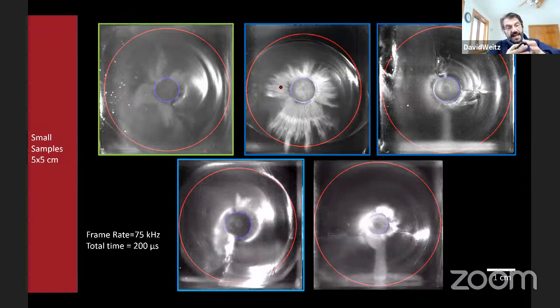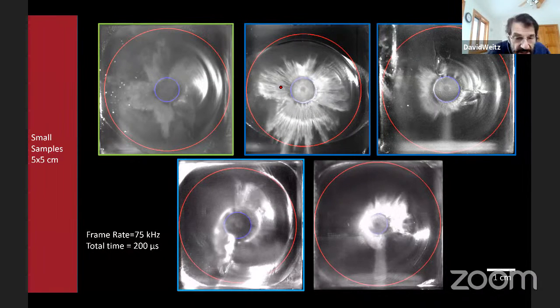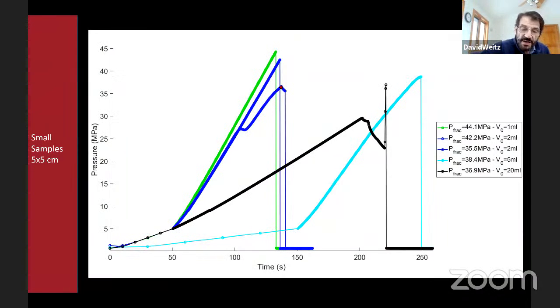And the reason for that is that you've compressed the fluid. Let me see if I have a, yeah, here you've compressed the fluid. This is what it looks like. This is the pressure as a function of time. You've compressed the fluid. You have to put a pressure now, it's tens of, 50 megapascals. This is, of course, what the yield stress of the sample is. The sample itself is of order gigapascal. Its yield stress is going to be something of a few percent. It's, in this case, 30, 40 megapascals. That's very consistent with it. So you compress it, and then you see the pressure fall off when it cracks.